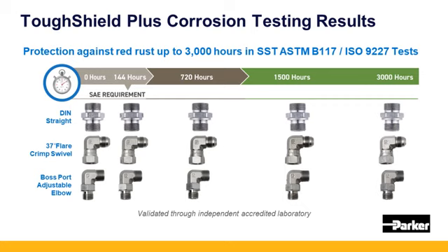So how do these products look in salt spray performance? What you see here is a modest representation of different products, whether it's a DIN straight fitting, a fitting that has crimp swivel nuts on it, a Boss adjustable elbow that has a backup washer and lock nut on it. These have been tested independently to ASTM B117 or the ISO 9227 equivalent. And so really the takeaway here is that from brand new, clearly up to the 144-hour SAE requirement, no corrosion, no base metal corrosion whatsoever, all the way to triple the SAE requirement, well past that to 1,500 and all the way to 3,000 hours, no base metal corrosion.